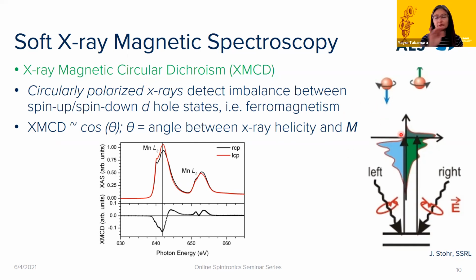And in particular, again, for the first row transition metal elements that we're interested in, we're looking at metal 2p to 3d transitions, and the 3d orbitals are the ones where we get that magnetism. So it's a really good way of probing what the empty states at the Fermi level are in those d orbitals. And now if we come in with circularly polarized X-rays, then the right versus left